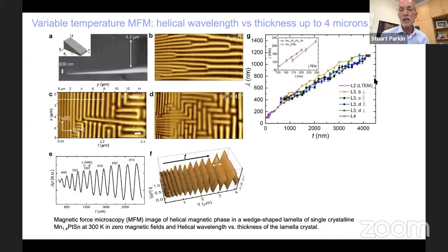And in fact, here it's even more dramatic. Now we have lamella that vary all the way from 40 nanometers to 4 microns. And you can see the period of the helix increases from 100 nanometers to more than 1 micron. So now we can see these structures even optically. And shown on the left of 4, firstly on the top left in A, you can see the lamellar wedge we've made, or Abbe has made. And then you can see in these 3 different magnetic force images, we can stabilize these helical structures in different directions by applying in-plane magnetic fields. And you can clearly see that these helical structures have their oscillation period only along two distinct crystal directions determined by the underlying crystal symmetry.